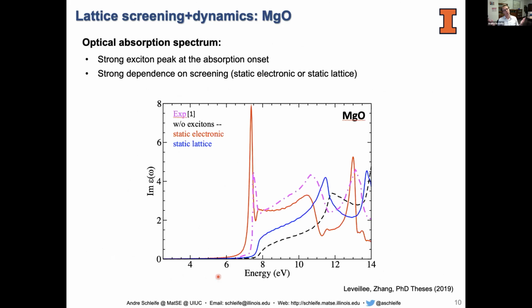Okay, let me show you the application. So far, this is work in progress. What I can show you so far is an application to bulk materials, in this case an insulator, magnesium oxide. What we calculated here is the imaginary part of the dielectric function. I said earlier that's a quantity that people can measure with, for instance, ellipsometry. Experimental data is shown in magenta here. The data without excitons, we don't need to look at too much here for this material. The difference is very large, and that's well understood.